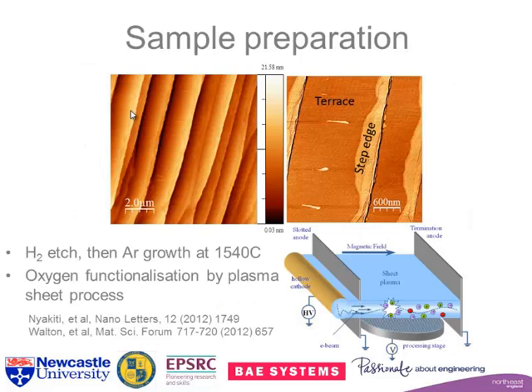Sample preparation, we put it through a hydrogen etch to completely clean and flatten the surface. This is what the surface of silicon carbide looks like. These are the step edges that result from the epitaxial growth. We can't grow it perfectly on axis. It doesn't work. We have to tilt the wafer slightly. So we get these step edges, and these are atomic crystal planes.